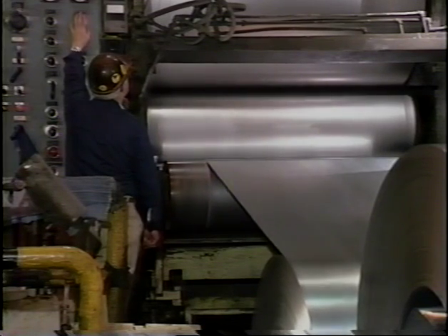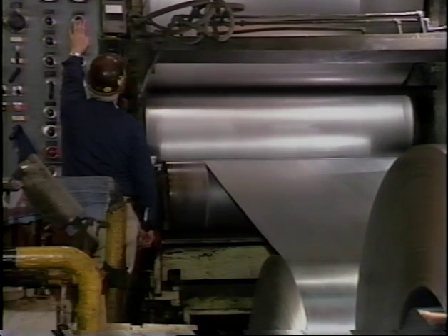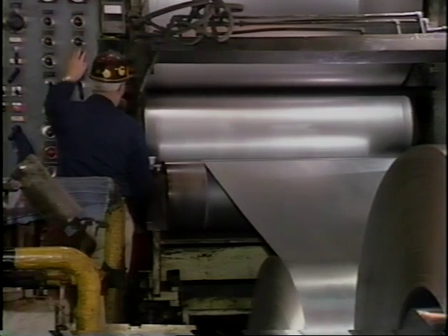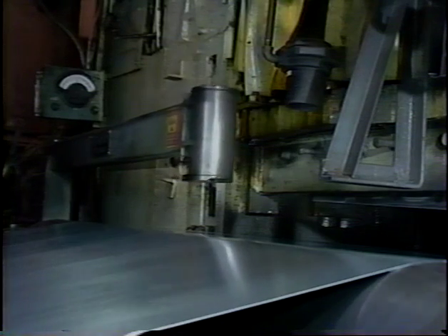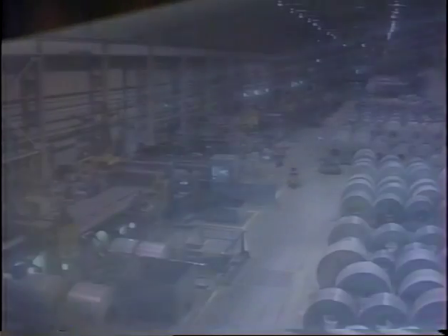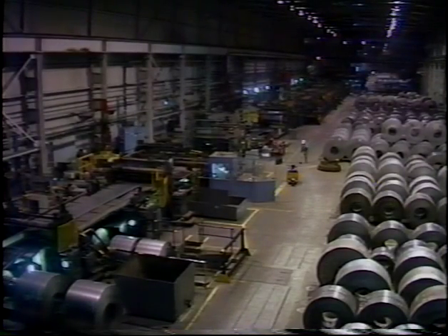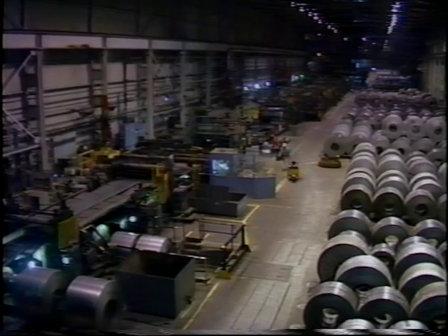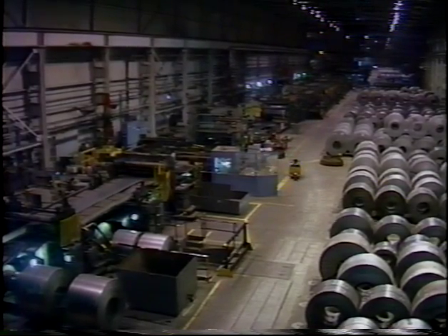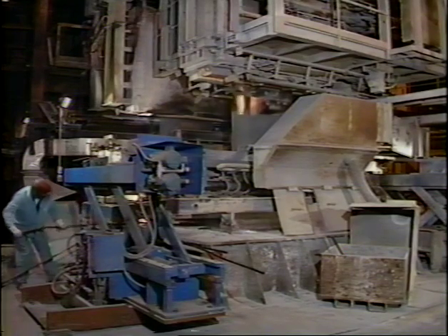The temper mill puts the finishing touches on the cold rolled sheet. Light temper rolling imparts the final hardness, flatness, and surface texture wanted by each customer. An X-ray gauge ensures accurate thickness, and oiling protects the surface of the steel during coiling and further handling. Pickling, cold rolling, annealing, and temper rolling prepare the sheet for the heart of our top quality process, the continuous galvanizing line. This is where the steel gets the zinc coating that protects it from corrosion.